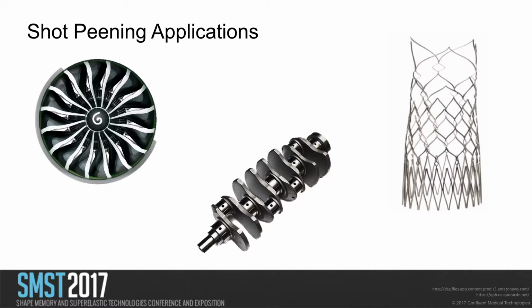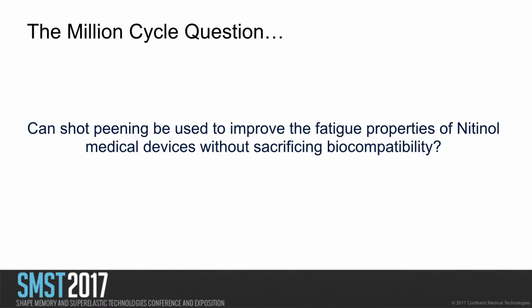Shot peening is a mass finishing process. You typically either take a pneumatic or hydraulic system and just spray a bunch of these beads against a substrate. And you can get material that's then impregnated into the surface. Unless you clean that, it can be a big issue with biocompatibility. So what we did is we asked ourselves the million cycle question of, can shot peening be used to improve the fatigue properties of Nitinol medical devices without sacrificing biocompatibility?